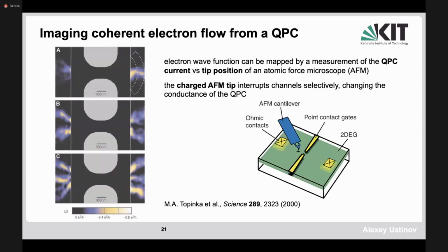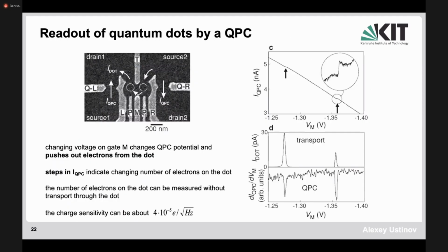I wanted to show here that these channels really exist, and people have been able to scan the cantilever of an atomic force microscope to measure the local electric influence. If you influence one channel or the other, there is a change in the current, and people were able to visualize these channels in the quantum point contact. It is not just the quantized conductance as a secondary demonstration, but also a direct indication of the presence of these low-dimensional transport channels in this low-dimensional structure. Now back to the qubits.